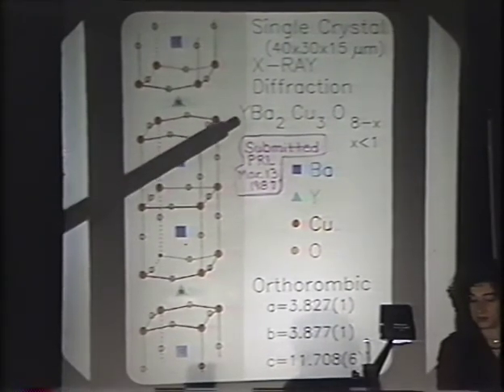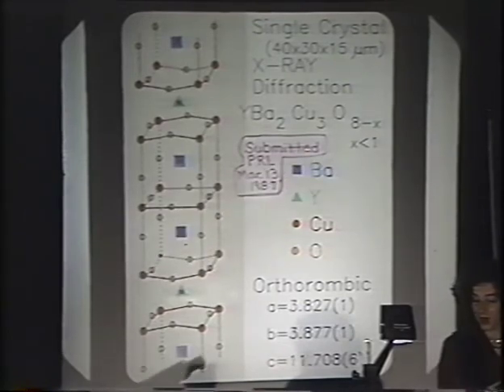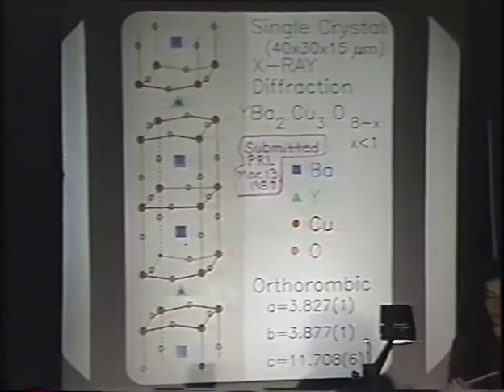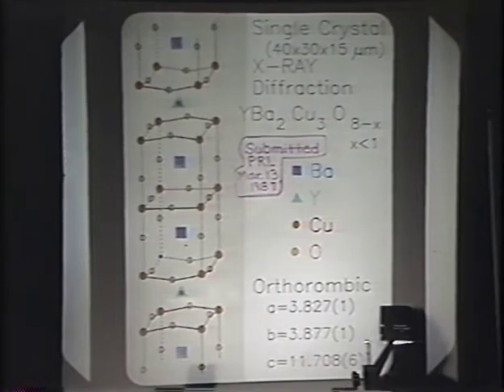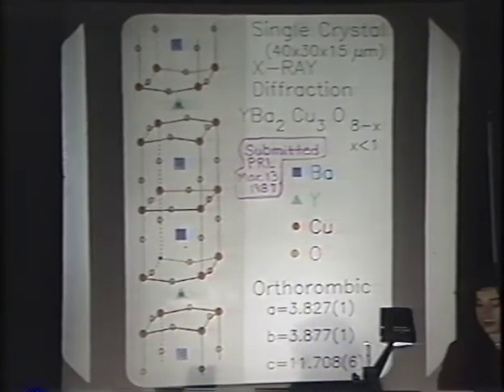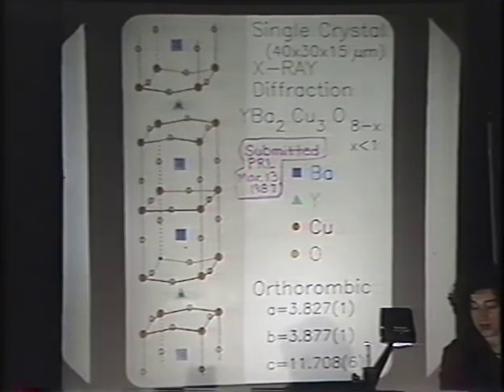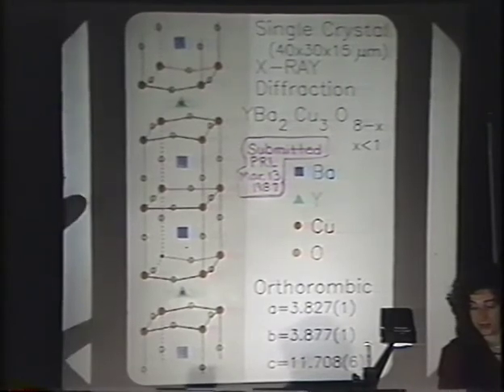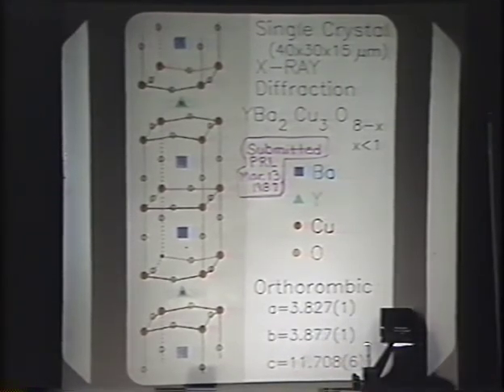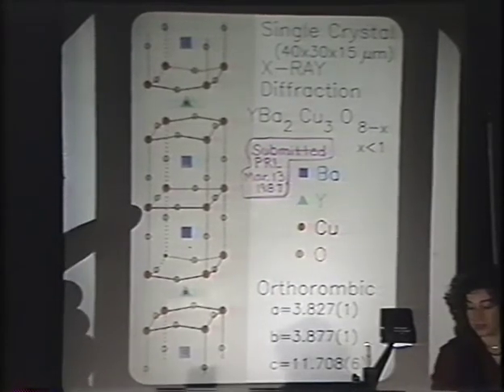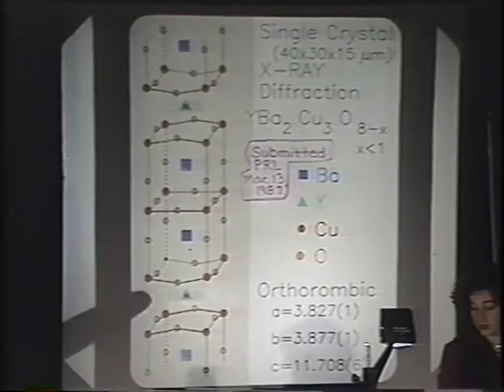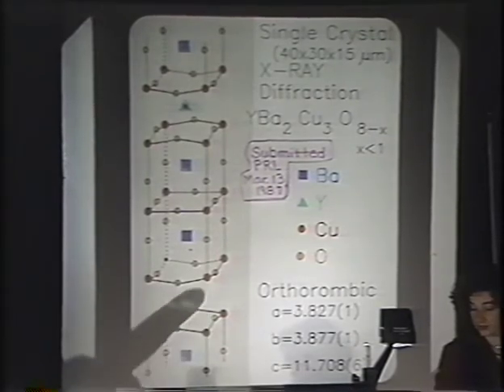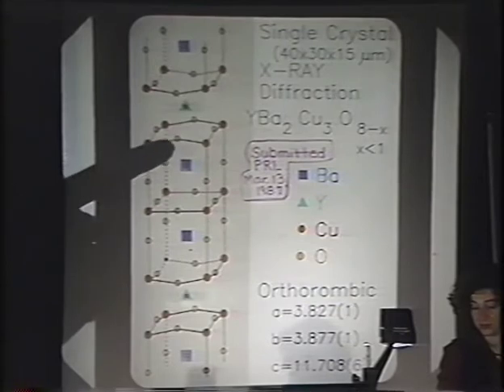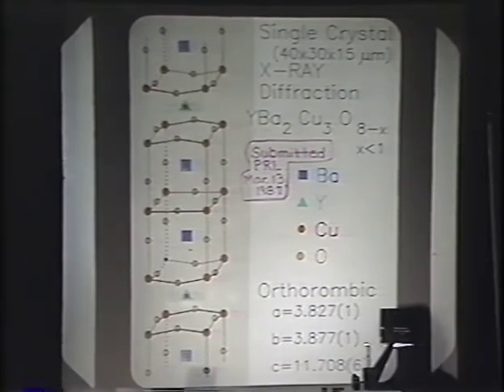This is the material that some people agree and disagree with on the oxygen. It is orthorhombic, and it remains orthorhombic down to 90 degrees without any further structural change. I'd like to point out that there are oxygens missing on the yttrium planes, which gives us three copper planes. So it's a 2D electronic structure. If there are further oxygen vacancies, which we believe are as high as one here, they would occur in this basal plane between the bariums. Notice also the slight distortion that remains down to 90 degrees, of the oxygen being pushed slightly higher in these planes. Thank you very much.